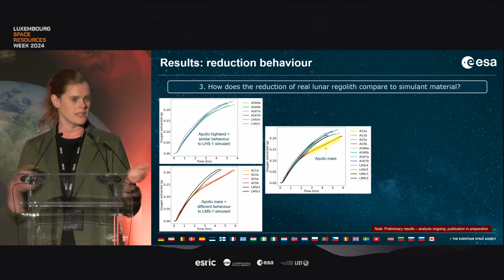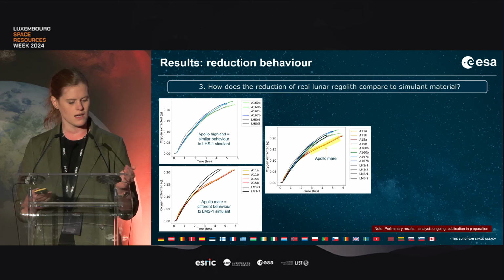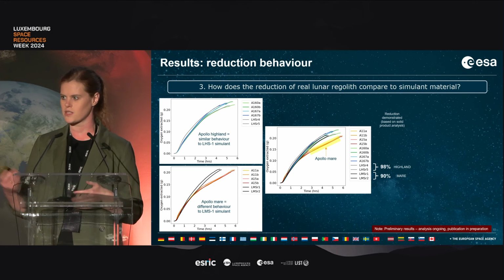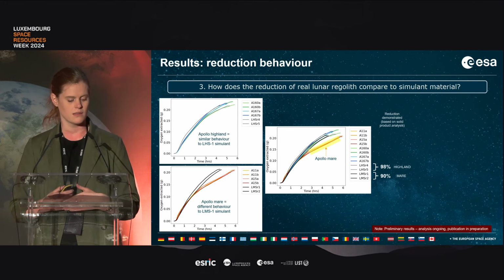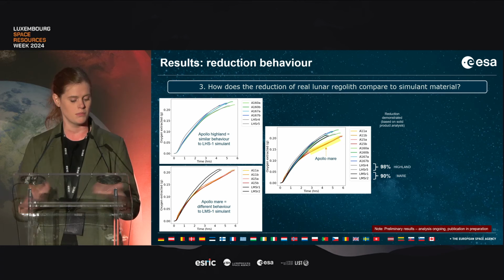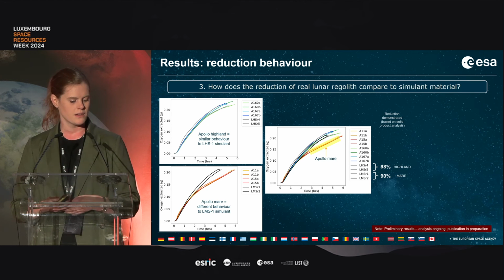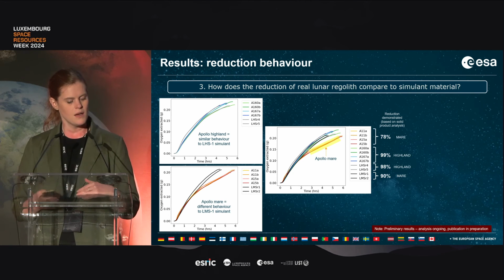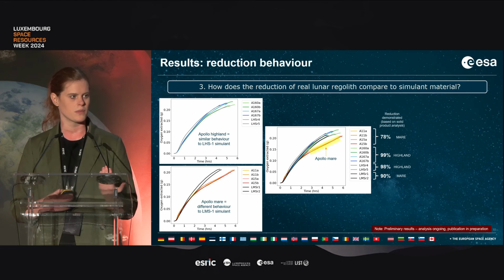And that's not to say that we didn't see any difference between the 2 simulant types, the same as Timon was presenting earlier. We in general see that the Highland material does reduce better than the Mare material, so 98 versus 90. But this discrepancy becomes much larger when we look at the results from the Apollo samples. So the Mare material, as I said, never got above 80%. That leads to the question of why. We don't have a really defined answer yet from this data set.